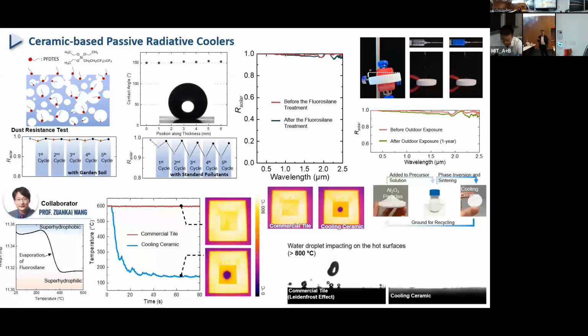Another spotlight of this paper, in collaboration with my colleague Professor Wang Zhengkai, is that we found that after adding a special layer of coating, the cooling ceramic becomes completely superhydrophobic and it can solve the problem of the Leidenfrost effect.